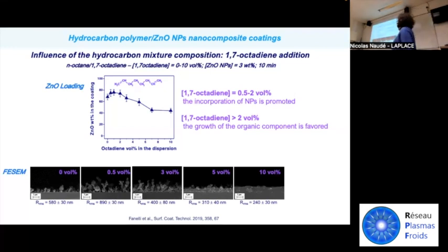we have now that the contribution of the organic component is promoted. From transmission electron microscopy investigation, we also had the feeling that if we are able to promote the growth rate of the organic component, we are also able to, in such a way, reduce the contribution from highly densely packed nanoparticle agglomerates.